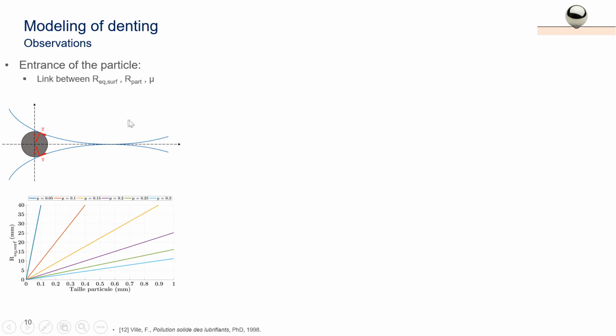You can make a simple mechanical model to see, depending on the friction coefficient, what you need to have the particle entering into the contact. If there is no friction coefficient, it will be ejected. And then depending on the size of the particle and on the friction coefficient, you can calculate the size of the particles that will enter into the contact.